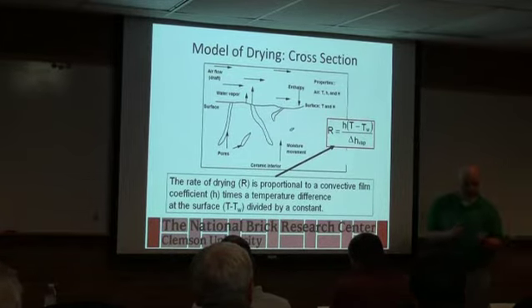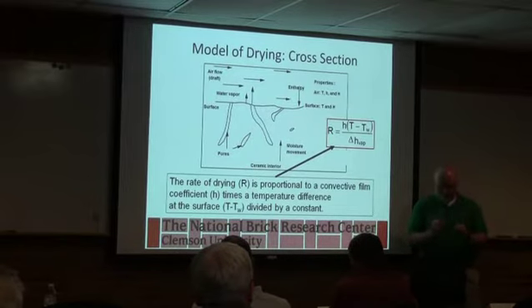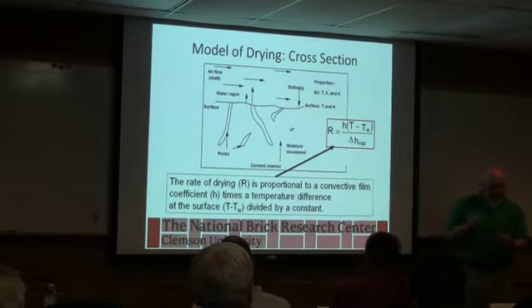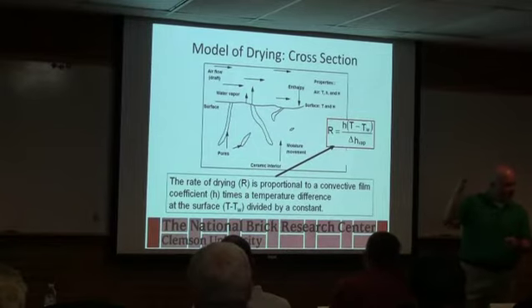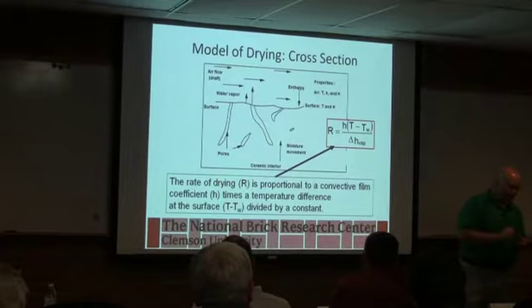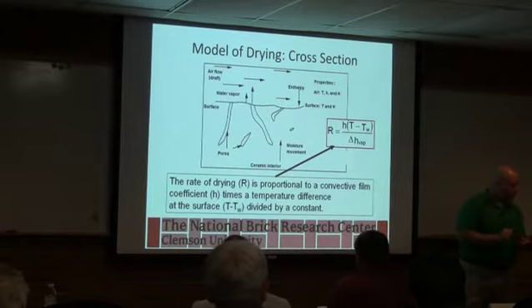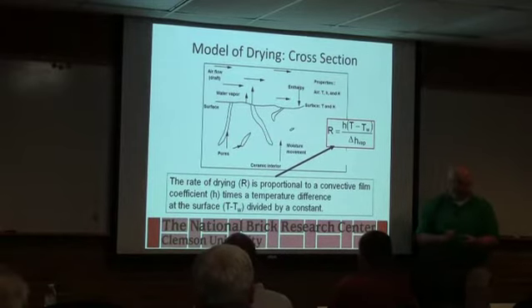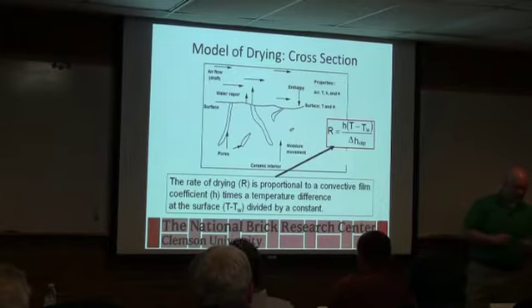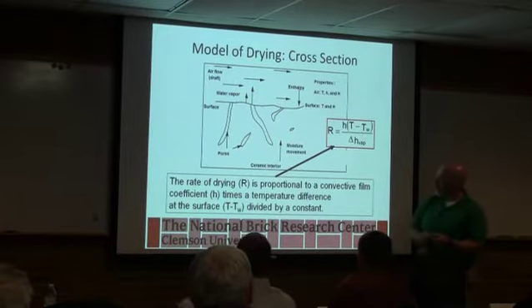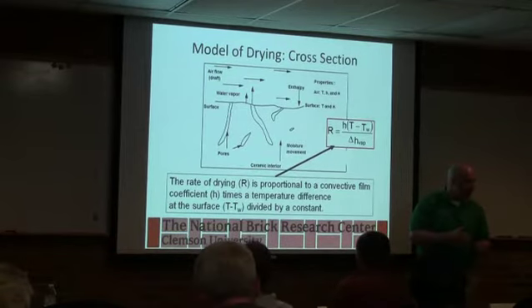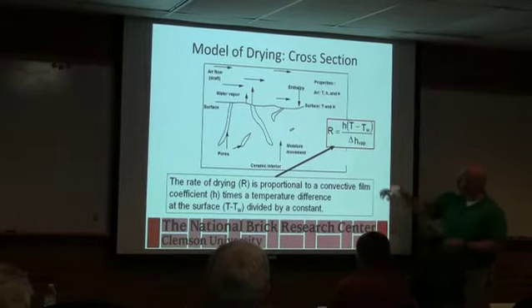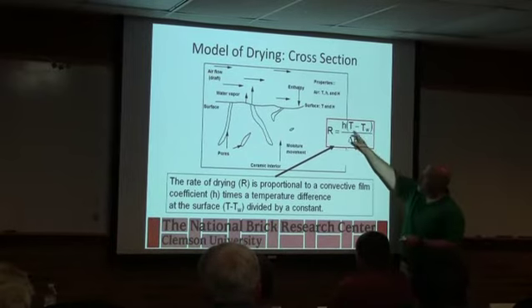But basically it's two thermometers side by side. One of them has a little sock over the end that you wet, okay, and you go in the dryer and you swing it around, and if the air is wet, not much evaporation will take place on that sock, and the two temperatures will be almost the same. Okay, it means a high humidity. If you go in and you swing it around and there's a big drop in the wet bulb one, you know you have a low humidity, and you can actually calculate the actual humidity off that. So what this is saying is that's the driving force for air movement.